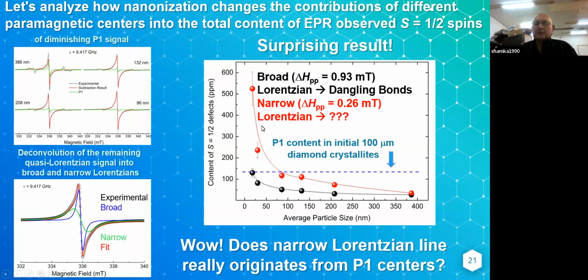Let's plot these results. When you decrease particle size, you can see that you have an increasing number of dangling bonds and increasing contribution of this narrow signal. Indeed, it's practically zero for larger particles. Then it goes up, up, up, up. And for smaller particles, it reaches what? Really? Wow. It reaches the initial concentration of P1 centers in large microcrystals. Oh, really? Does the narrow Lorentzian line originate from P1 centers? Most probably yes.